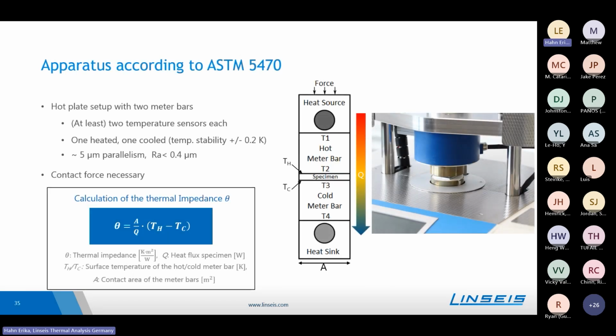As indicated before, the instrument is built according to a standardized method, the ASTM 5470 norm. The norm describes quite in detail how the instrument should be set up. Mainly, we have two plates. We call them meter bars, and these have temperature sensors built inside, so thermocouples. For the measurement, the sample will be clamped in between those two meter bars. One of the meter bars, which is in our case the upper one, will be heated and the lower one will be cooled so that we will have a temperature gradient over the sample and thus a heat flux through the sample. To enhance the contact between the material and the meter bars, we also need some contact force, as within the THB tests.